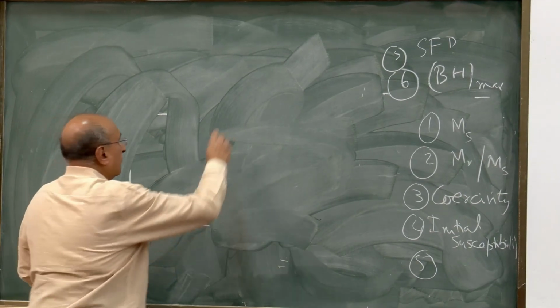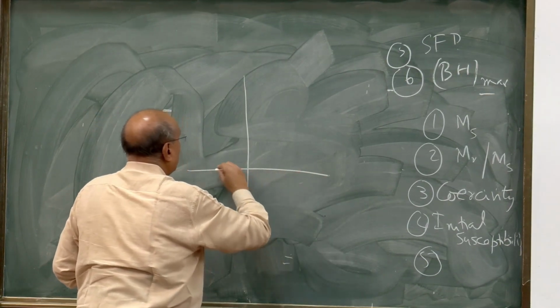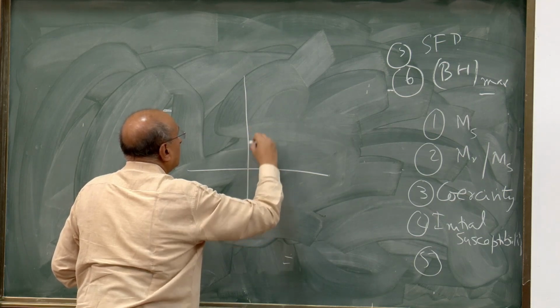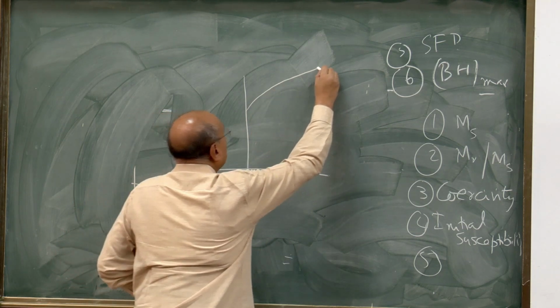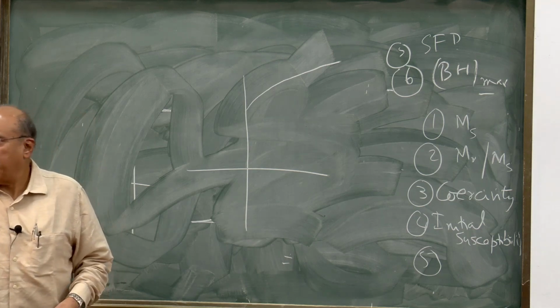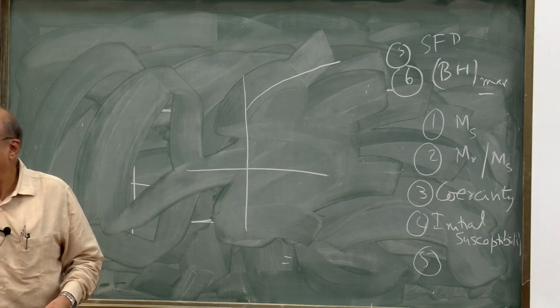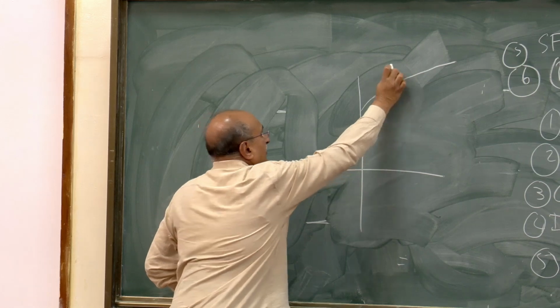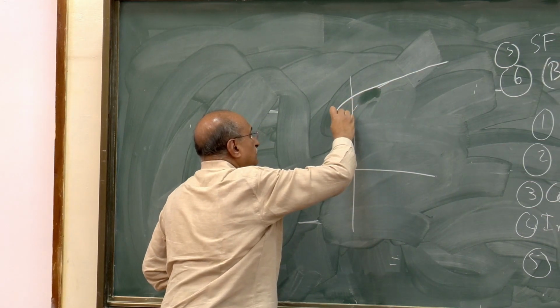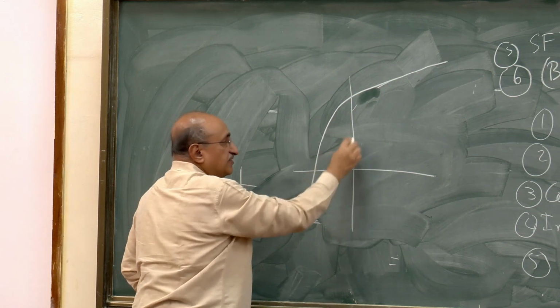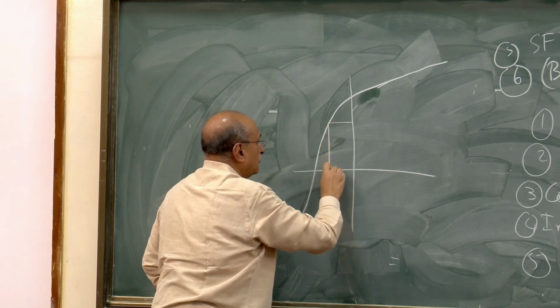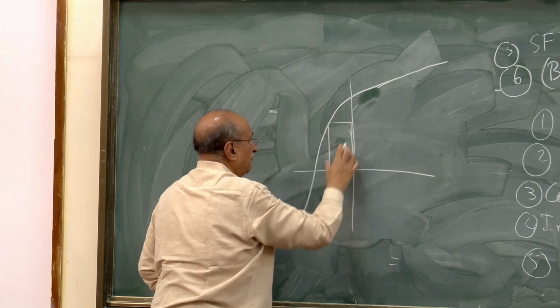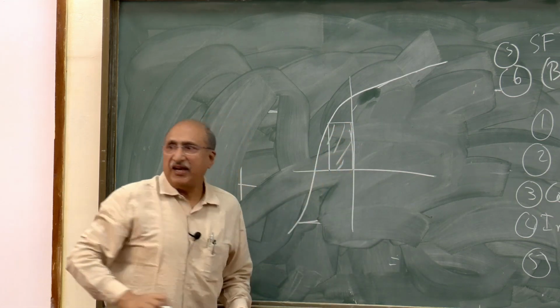If you plot the BH curve, it will not saturate because B is equal to H plus 4 pi M. As you keep on increasing H, it will still continue with a linear slope. Now, this is the second quadrant. You try to fit a rectangle wherever it is maximum under the curve. That's what is called BH max. Essentially, it tells you the energy stored inside a permanent magnetic material. So the larger the BH max, the better the permanent magnet.